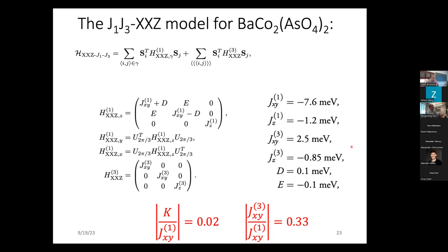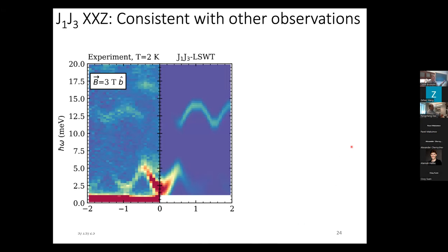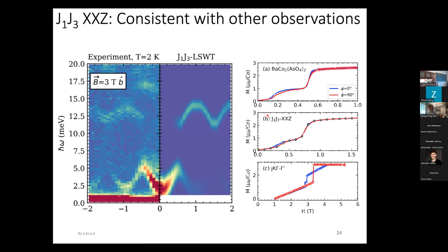And so we are now going to take that model and calculate things that we've observed experimentally. And one of those is, of course, the excitation spectrum at 3 tesla. And so that's now being calculated here. This is just using linear spin wave theory, actually. And so it produces this mode as well as this mode at 3 tesla, and this was a 2 Kelvin measurement.